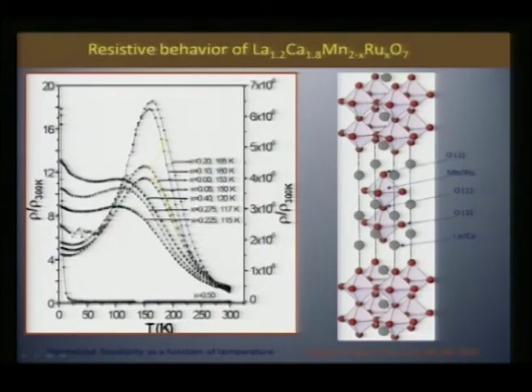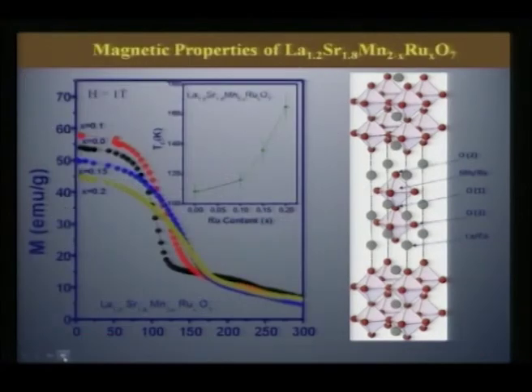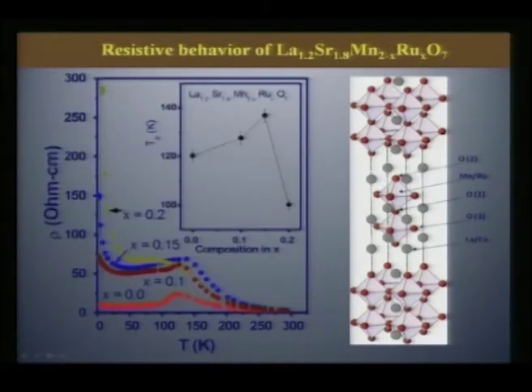You would see this as the metal insulator transition for your parent compound, whereas if you substitute ruthenium, the metal insulator transition shifts to the right side when you have calcium, and it is much more interesting if you are going to substitute ruthenium keeping strontium instead of calcium. You would see the ferromagnetic transition is now on the increase from 110 to nearly 170 Kelvin. An increase of about 60 Kelvin you can bring about if you substitute ruthenium with a bigger size cation. The same is true in the metal insulator transition, where you see a clear increase in your metal insulator transition going hand in hand with your magnetic ordering.